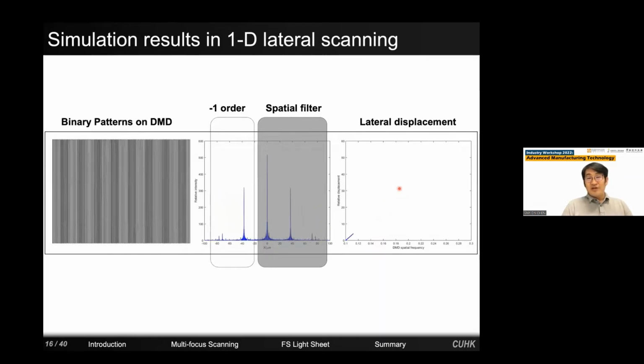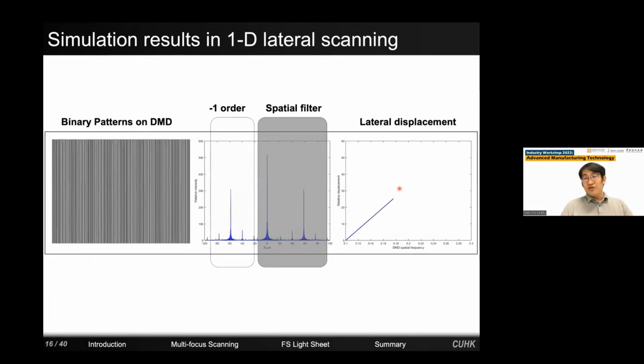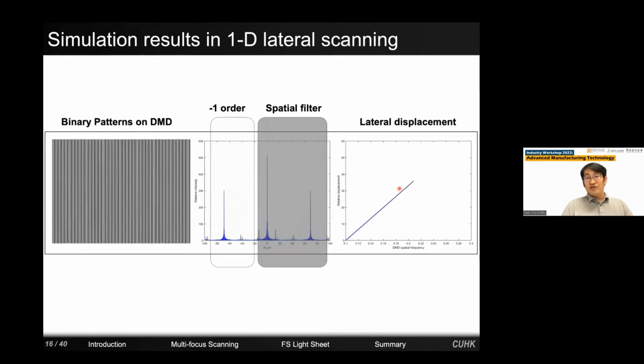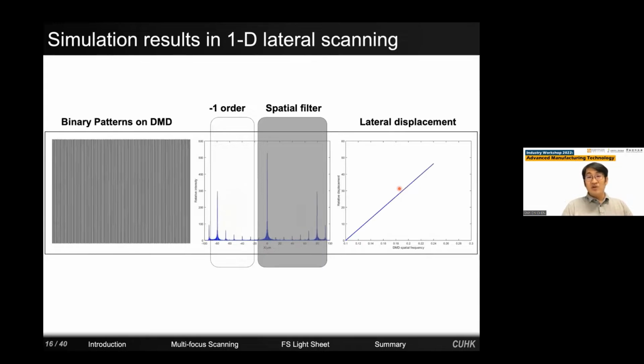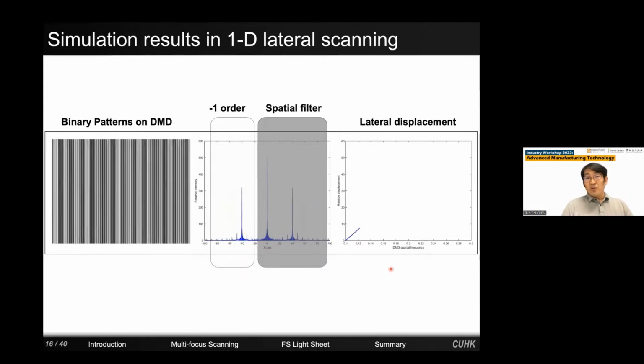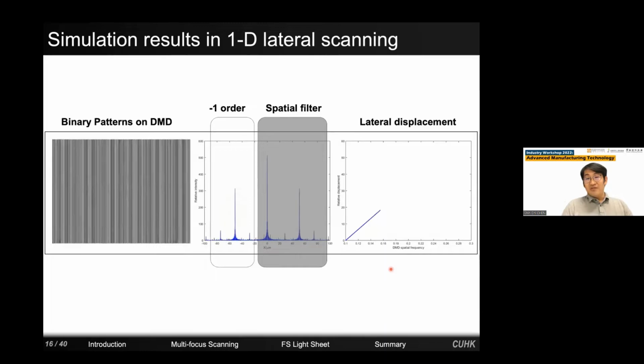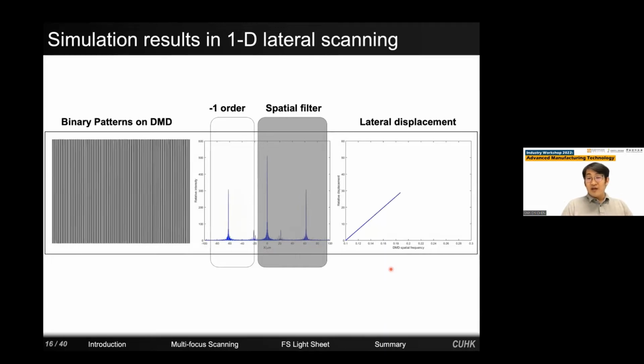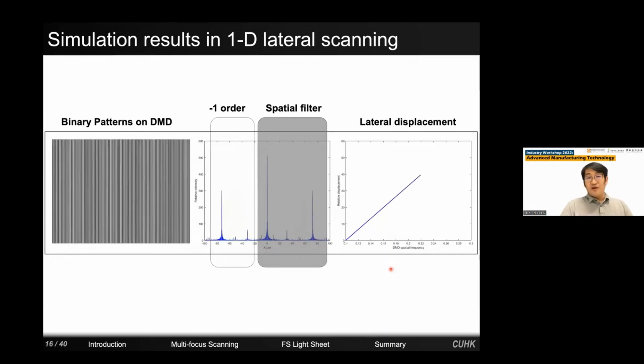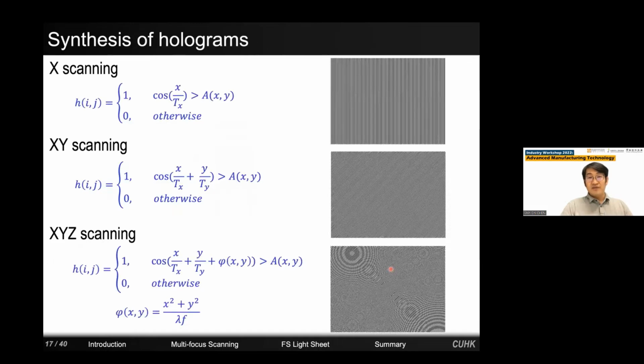So based on our calculation, under a 40x objective lens, we can quickly control the focal point in the axial direction for about 500 microns and laterally for about 200 microns, with a minimum step size of about 100 nanometers, which is sufficient for our target application. Then we briefly talk about how holograms are synthesized.